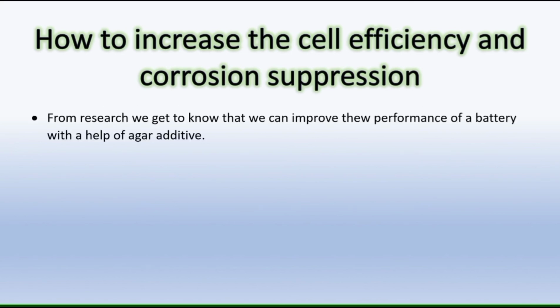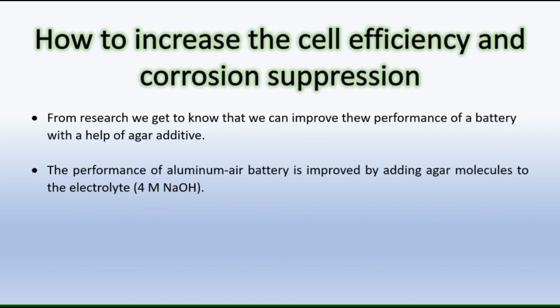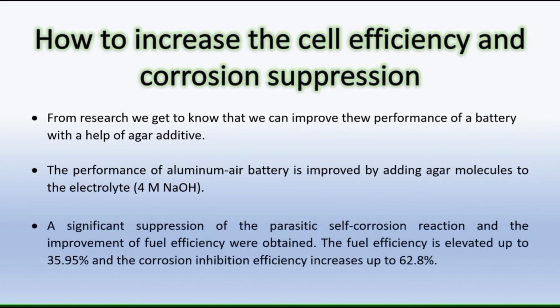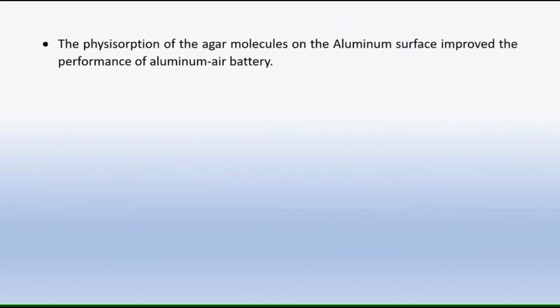After reading several research papers, we got to know that agar is the best material as an additive. The performance of the aluminum air battery is improved by adding agar molecules to the electrolyte. A significant suppression of the parasitic self-corrosion reaction and an improvement of fuel efficiency were obtained. The fuel efficiency is elevated up to 35.95% along with the corrosion inhibition efficiency. The physisorption of the agar molecules on the aluminum surface improved the performance of the aluminum air battery.